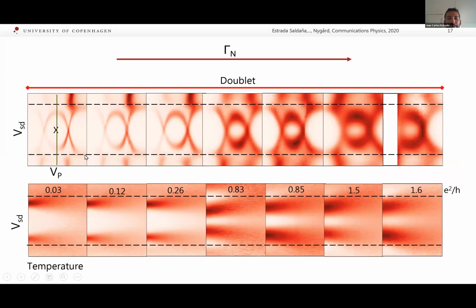And what we find is that as we increase the gate voltage, we go from very faint peaks to very broad and large conducting peaks. And this happens because we're equilibrating the couplings between the left and the right side. And here in the bottom row, I wrote some of the maximum conductance of the peaks. And we go from 0.03 to 1.6, so fairly conducting. And again, we're going to take line cuts in the middle, and we're going to see the temperature dependence of the peaks. And what we see is that all of them shift at more or less the same rate of 100 microvolts per Kelvin.